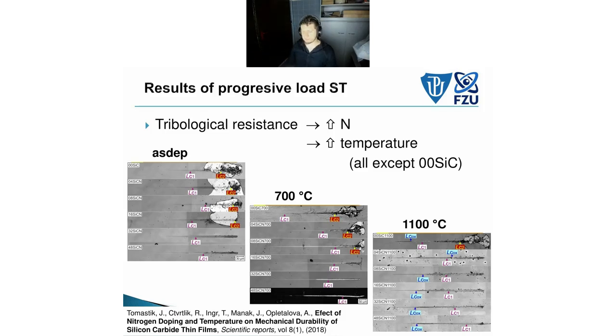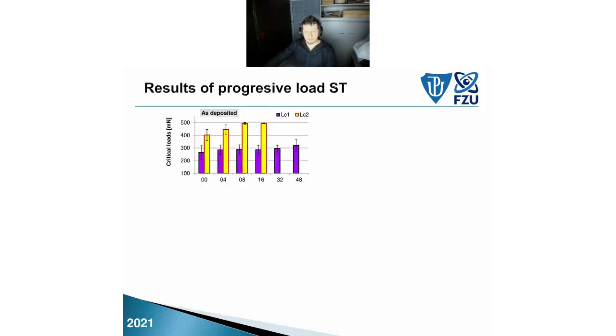And after annealing, the most interesting thing, silicon carbide, let's say, deteriorated. There's some brittleness, some extensive cracking, but silicon carbonitride actually increased its properties. So we can see some cracking at a low nitrogen content, but not at a higher nitrogen content. For instance, in the middle sample, 16 SiCN, we can see some cracking in the as-deposited case, and we cannot see it after annealing. So apparently there are some effects of this change in structure on mechanical properties.